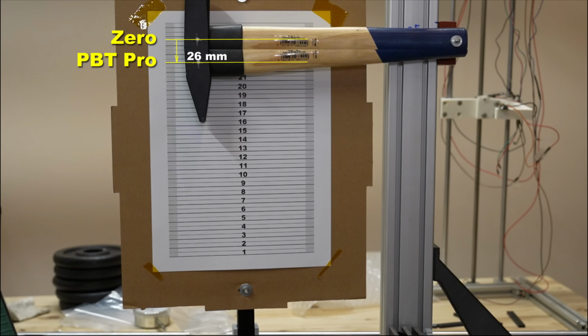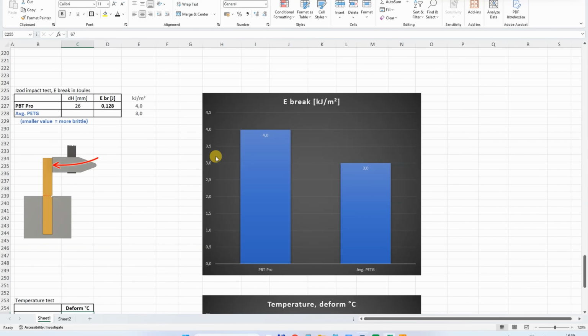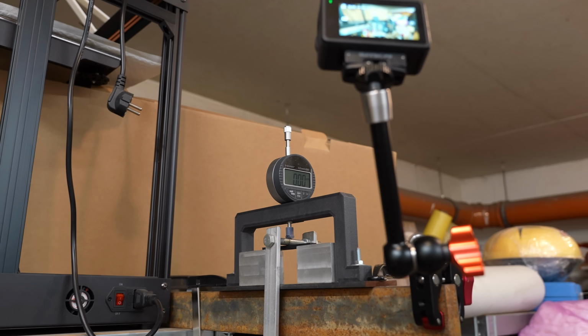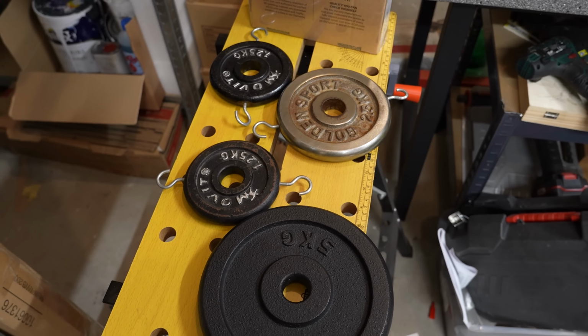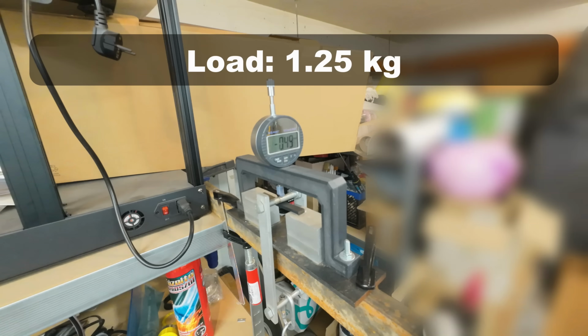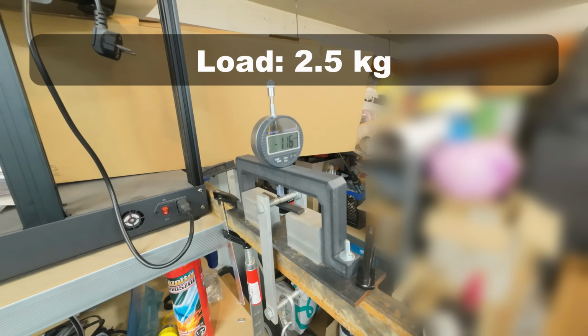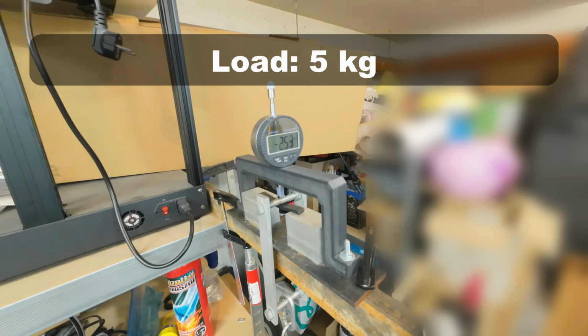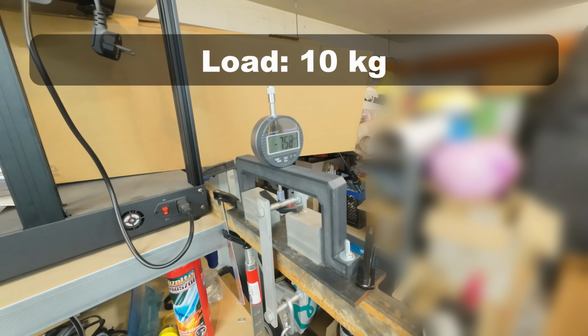These are two edge positions of the hammer, and from the difference in height I can calculate the breaking energy. And here I can see the first advantage of the PBT Pro compared to the average PETG. It is slightly tougher even if it is reinforced with glass fibers. And now the 3-point bending test, with these loads, which will be placed one by one, and I will measure the deformation after 1, 30 and 60 seconds. Currently under 1.25 kilograms, I pay attention that even now during this 1 minute it constantly deforms. This is now under 5 kilograms, and under 10 kilograms it couldn't even survive this 1 minute.